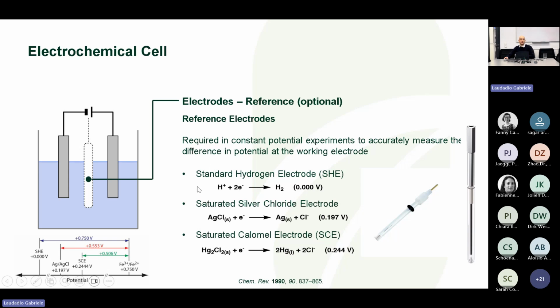In particular, the three most famous reference electrodes are the standard hydrogen electrode, the saturated silver chloride electrode, and the calomel electrode. Obviously, the calomel is now less and less used because of the involvement of mercury, which is toxic, as we know, and the standard hydrogen electrode is very complicated to use because we have to make sure that the hydrogen is evolving very well in order to keep the voltage stable at zero. So in organic synthesis, we are more prone to use these two electrodes instead. And for the reasons that I was saying before, usually saturated silver chloride is the one that is the most used.